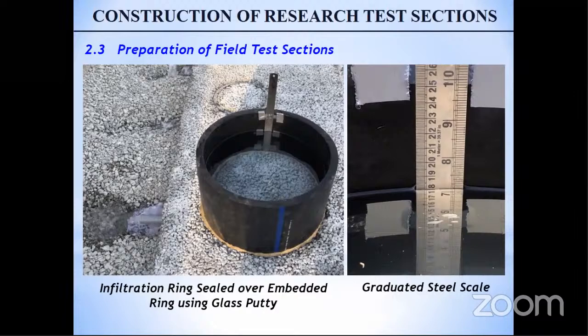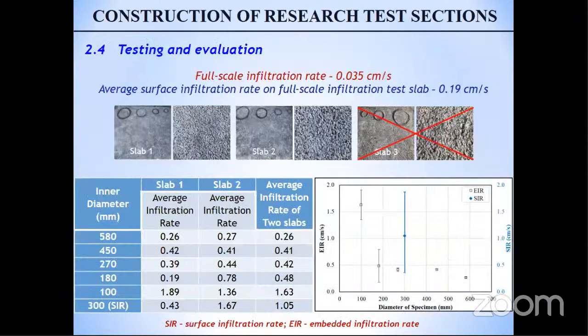As you can see, this is basically an infiltration ring which was placed over an embedded ring in order to investigate the infiltration rate of the system. On the right side, if you see, there is a small pipe which is projecting outwards from the pervious concrete layer. So again, what we did here was we filled up this ring with a designated amount of water. In the meantime, we kept the pipe outlet closed, and once the initial head was noted, the outlet was opened and the water was allowed to pass through the system. Again, the time taken by the water to fall from initial to final head was noted, and Darcy's principle was used to investigate the infiltration rate.